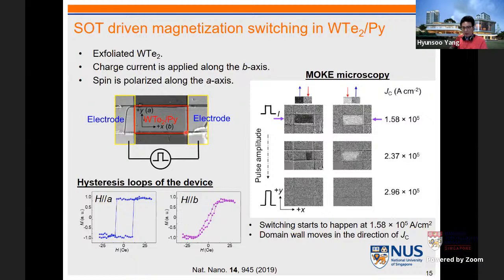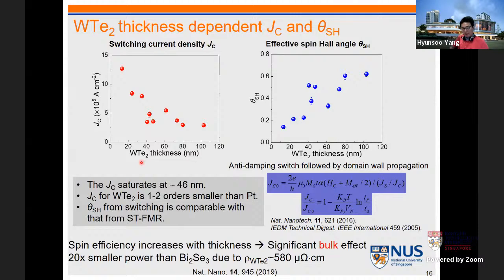So basically, we do a very similar approach, having this tungsten ditelluride, a prototypical Weyl semimetal, then we deposit permalloy on top, then we make some square magnetic piece, then apply current from the left electrode, then look at the switching, and we can also apply current from the right electrode, and we can go back to the initial configuration with a current density a few times smaller than that of a topological insulator. And once we study as a function of the tungsten ditelluride thickness, the current density scales down. Once we convert to effective spin Hall angle as a function of thickness, it initially increases and kind of saturates, but we couldn't really measure much thicker because it's too thick. So if you look at this thickness trend, this increasing trend and sort of saturating mimics that of platinum. So that indicates that we have a significant bulk contribution in this case.